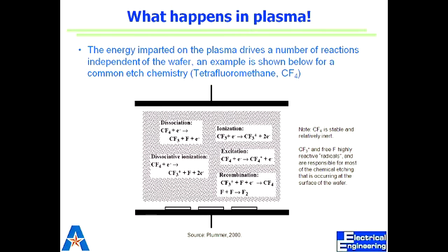Initially, yes, when you provide more etchants, the etch rate increases. It keeps increasing up to a certain level. After that, if you increase the pressure more, meaning you introduce more etchants, this recombination comes into effect.